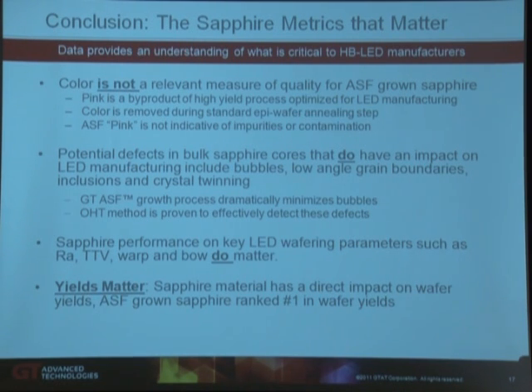Potential defects in bulk sapphire cores that do have an impact on LED manufacturing include bubbles, low angle grain boundaries, inclusions, and crystal twinning. The GT-ASF growth process dramatically minimizes bubbles, and the OHT method is proven to effectively detect these defects. We at Crystal Systems do not ship product with these defects or with any inclusion zones in our cores.